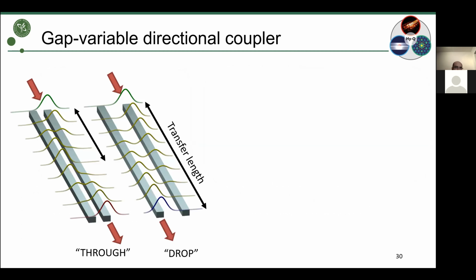So let me give an example of these mechanical devices. For example, a gap-variable directional coupler is the most famous example. And the idea is simple. You have two waveguides that are very close to each other. Here, the nano distance is very important. And they're close enough so that their confined fields actually leak a little bit into each other. So when you send light into one waveguide, it starts to move into the other waveguide and vice versa. And now if you're changing the distance between the two waveguides, you can control how quickly this light transfers from one waveguide to the other. And this way you can control where the light comes out.